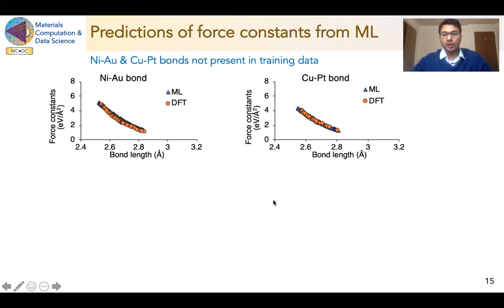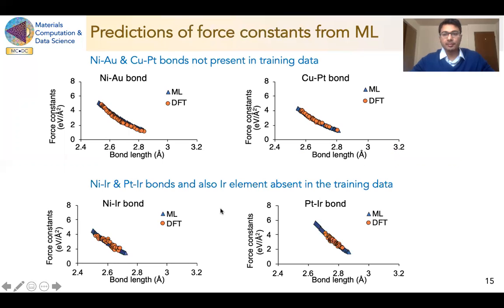Now we also tested our model with some other scenarios. So for example, force constants of nickel-gold and copper-platinum bonds are also predicted using the machine learning model. And when these bonds are not present in the training data, here also you can see that the predictions are very accurate. Similarly, we have predicted the force constants of nickel-iridium and platinum-iridium bonds when these bonds are not present, and also the iridium element is not present, meaning iridium based bonds are not included in the training data. So overall, our model is able to predict the force constants and its performance is quite well.